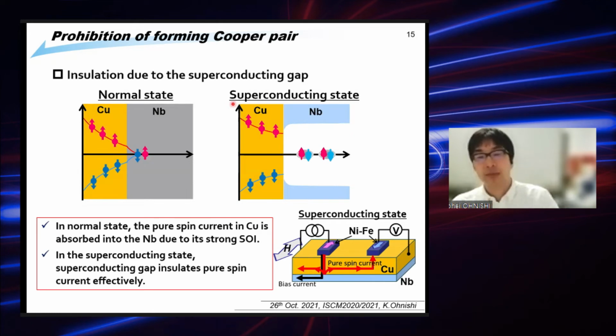This can be reasonably explained by the schematic shown here. In this scenario, in the normal state, the pure spin current in the copper is absorbed into niobium due to its strong spin-orbit interaction. So by this, the pure spin current should be absorbed so much. But in the superconducting state, the superconducting gap suppresses this absorption, so the pure spin current is transmitted effectively.